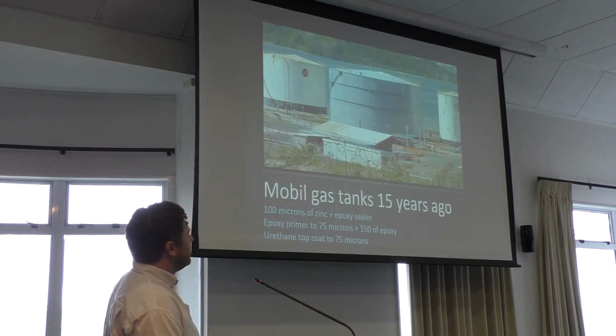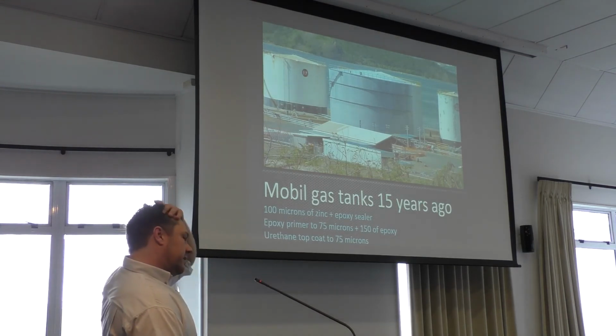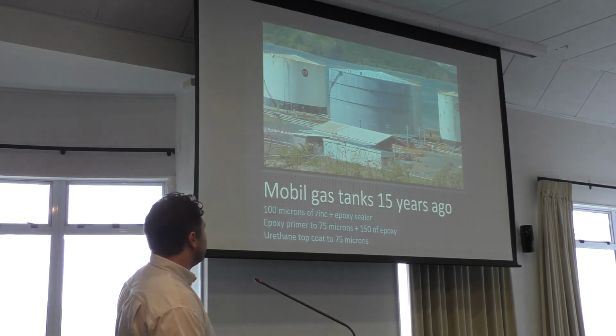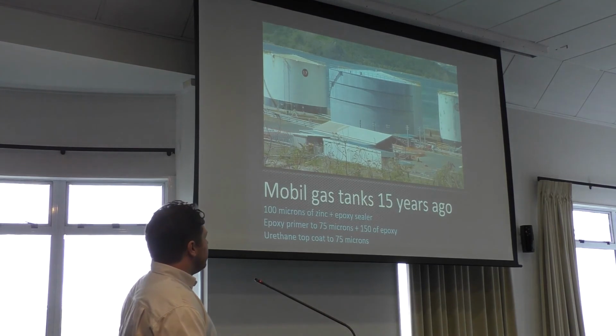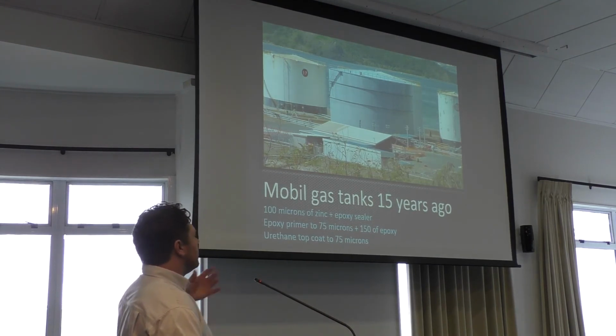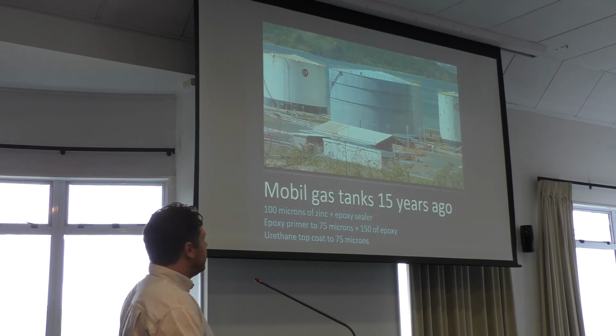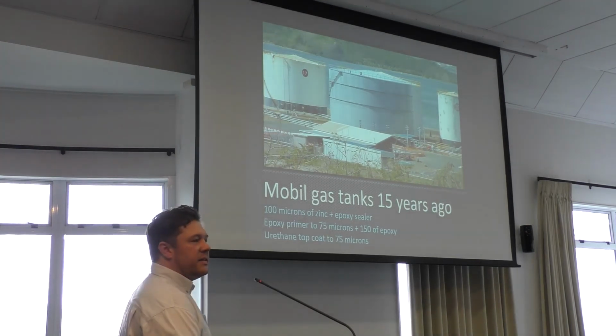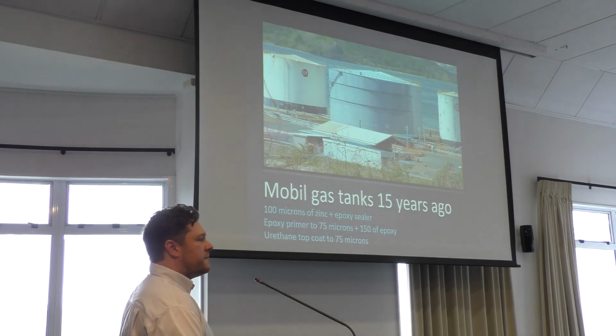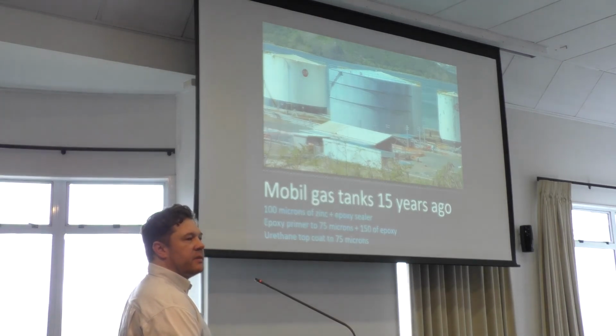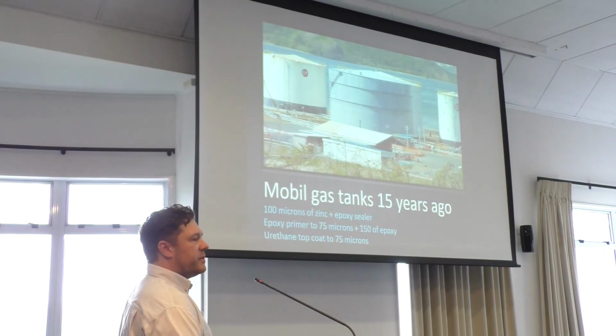So the Mobil gas tanks are actually situated fairly close to the gas tanks that we just saw before. 100 microns of zinc plus epoxy sealer and an epoxy primer to 75 microns plus 150 of epoxy on top, and then urethane as well. You can see that's a reasonably thin coating of metal spray and then a lot of paint on top. So that's a pretty good coating.